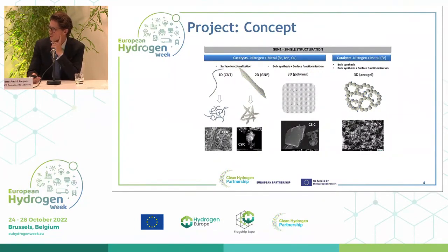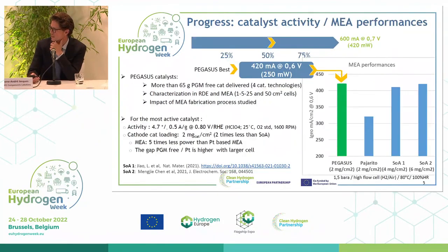We made modification of carbon nanotubes, modifications of graphite carbon, modifications of graphene layers, and also we developed our own synthesis based on sol-gel protocols. That is a different way that we use to make our catalyst. And finally, in that project, we observed good performance for our catalyst, comparing the performance of our catalyst with the state of the art available, either commercially available or given by the advisory board members, and also comparing to the data that are publicly available in the literature during the course of the project.